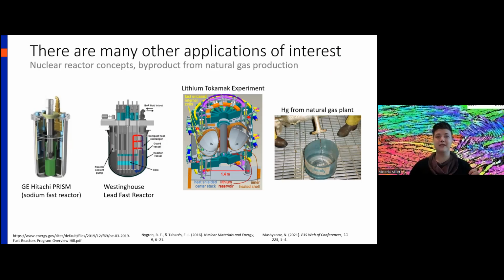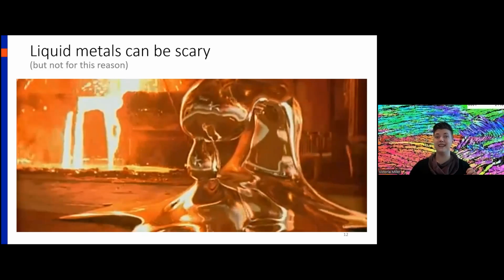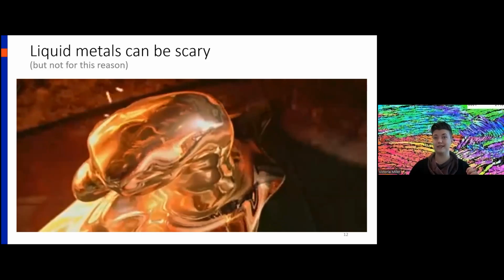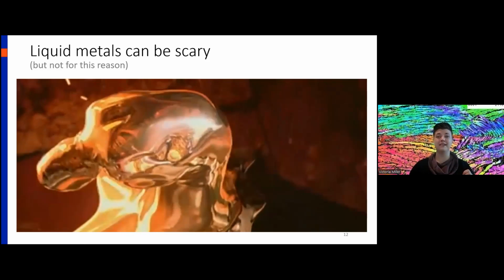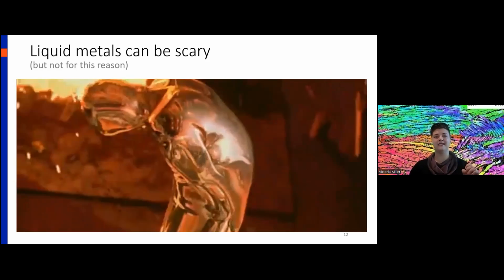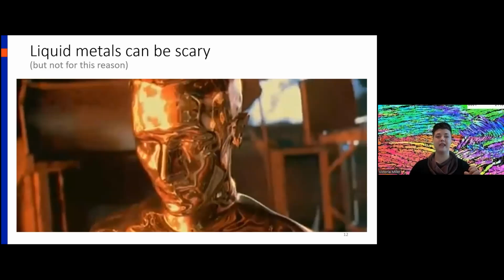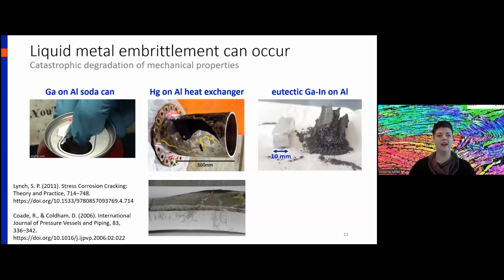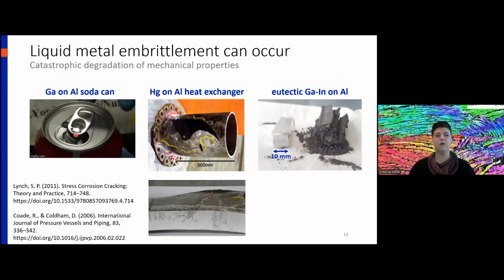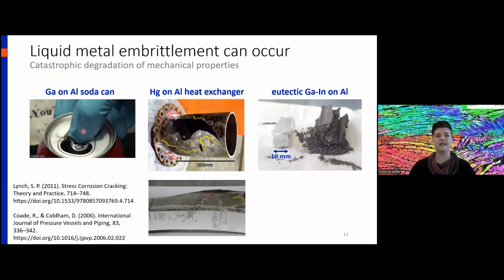However, liquid metals can be scary, and not necessarily for Terminator-related reasons. Liquid metals, when in contact with certain solid metals, can create embrittlement and catastrophic degradation of material properties. So here is a GIF of gallium on an aluminum soda can. And you can see once the soda can has been exposed to gallium, it's very brittle and you can just punch your finger right through the top of it.